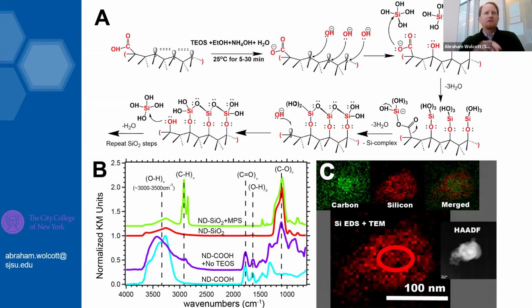What's interesting is, and I'm not sure if any of the silica chemistry folks are out there, but besides Nicholas, in the route that we use, which we borrowed from Peter Sigler, we don't add PVP. All we use is TEOS, a majority of ethanol and ammonium hydroxide, and a little splash of water. So it's very clean. There are very few things that go in there. We don't need a polymer, and we can get a high level of control on the thickness of the SiO2.